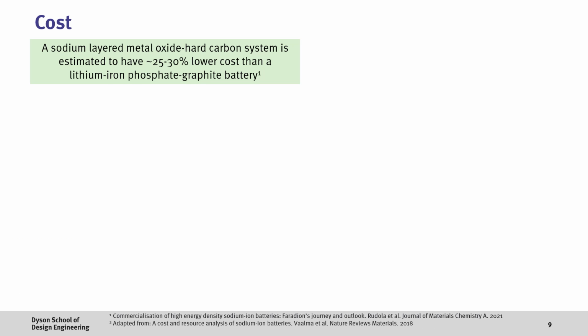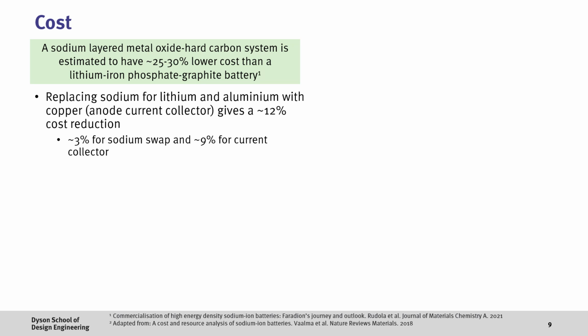Now, one of the key arguments for the use of sodium-ion batteries is that they're lower cost, and this deserves a bit more discussion. It's been estimated that at scale, a sodium-ion battery with a layered metal oxide cathode and hard carbon anode will have 25 to 30% lower material costs than a lithium iron phosphate battery. If we unpack this a bit more, we know that two of the main differences in a sodium-ion cell versus a lithium-ion cell is that they replace lithium and copper with cheaper sodium and aluminium, which gives around a 12% cost reduction, with most of this being due to the aluminium current collector.